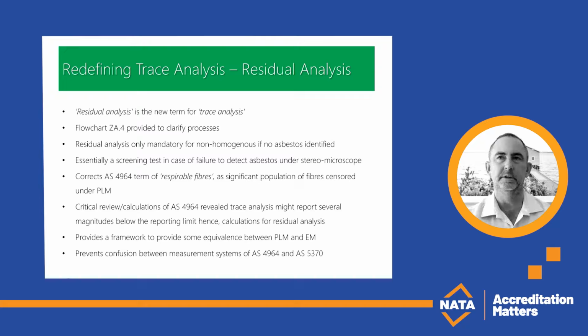So it's also important to note that AS 4964 incorrectly suggests that trace analysis under polarized light microscopy can accurately detect respirable fibres. Because of the limitations in dispersion staining for fibres less than 1 micron in width, this severely censors the true concentration of respirable fibres that only electron microscopy can reveal. And this is why PLM is not a valid method for a risk assessment, as it censors respirable fibres. For instance, how many fibres do you think you'd miss when conducting fibre counting using phase contrast microscopy compared to PLM? Because this would be a gross underestimate, and you'd never pass proficiency testing criteria during this method.